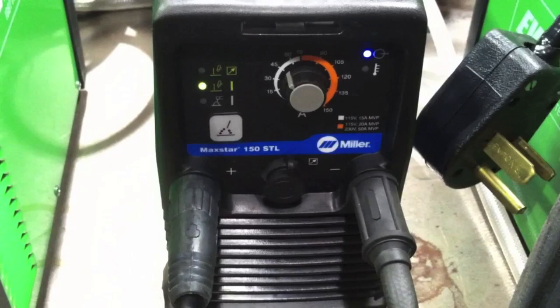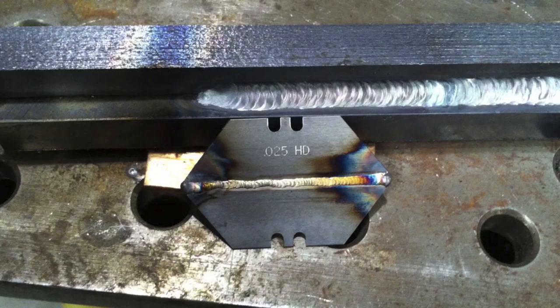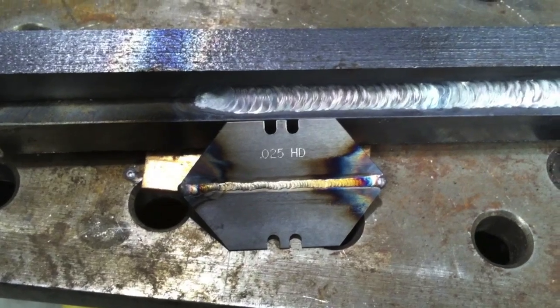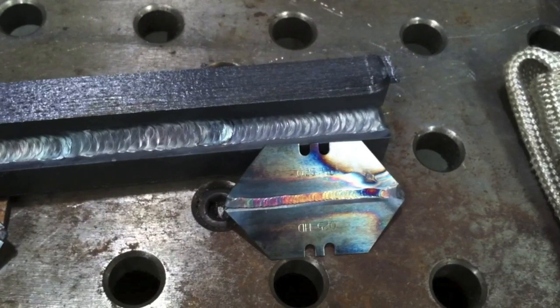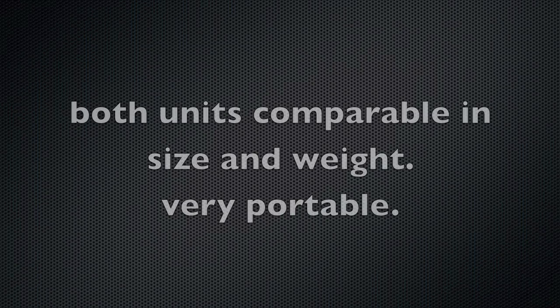You be the judge. Maybe I'm just not that picky, but they're very similar on the low end and the high end, other than the Miller being a little bit lower on the low end, I think. So there's the Miller welds, the thin box cutter 25 thousandths blade and then the 2-pass thick weld. And here's the Everlast box cutter blade and then the 2-pass thick weld that I did with it.